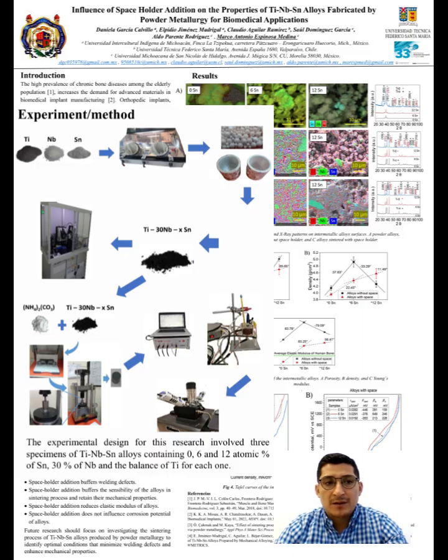First, pure powders of titanium, niobium, and tin were milled in a high-energy mill to obtain powder alloys, and some samples of the powder alloys were mixed with ammonium carbonate as a spaceholder agent. After that, samples of the powder alloys were compacted and sintered to obtain cylindrical solid samples. These alloys, powder and cylindrical, were characterized by scanning electron microscopy and X-ray diffraction. In parallel, some mechanical properties such as porosity, density, and Young's modulus, as well as the corrosion resistance, were tested.